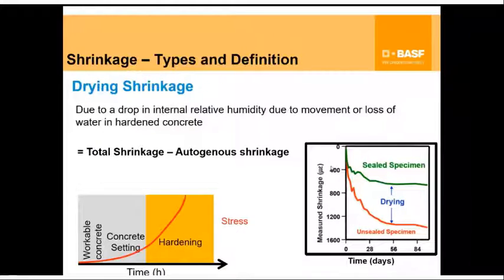Drying shrinkage happens pretty much around 24 to 28 to 30 days. That's the area to look out for. Anything above 28 days is when you look out for this kind of stress. Like I said, if the stress is higher than the strength, only then you get a crack. But in this case, the concrete has already hardened, right? We're talking about 28 days.